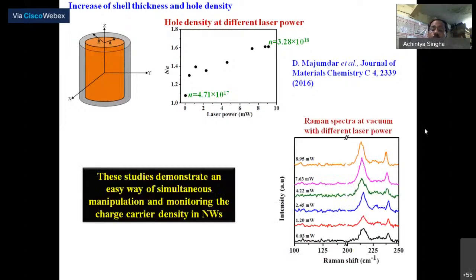And in the bottom right side you can see some spectra. Those spectra we measured using the same experiment, but in vacuum. As there is no oxygen, oxidation is not occurring on the surface, and that's why electrons are not trapped by the surface of the nanowire, and there is no presence of the CPLP, meaning the coupled plasmon phonon mode. So in this experiment we can tune the charge concentration within the nanowire, and by Raman spectroscopy we can monitor this charge concentration from the CPLP mode.